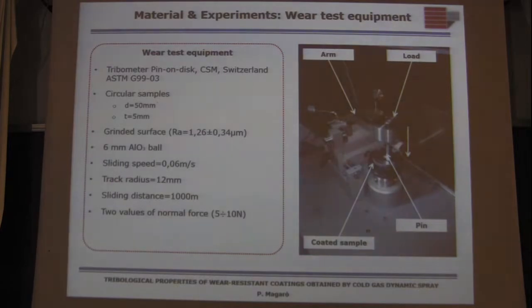On the other hand, tribological experiments were carried out using a pin-on-disc standard method, and for this case some samples characterized by a grinded surface were prepared. The tests were carried out using a 6 mm alumina ball with a sliding speed equal to 0.06 meters per second, a track radius equal to 12 millimeters, and a sliding distance equal to 1,000 meters. In particular, two levels of the normal force were evaluated, 5 Newton and 10 Newton.